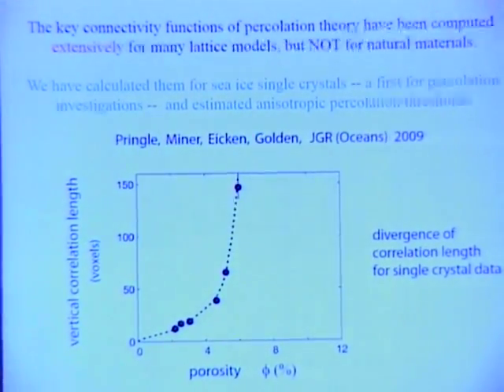Now I've seen hundreds of papers where they compute these functions for lattice models. I've never seen a paper in the literature where they actually do this for real materials. You can't turn a knob, for example, and change the conductivity of pores in sandstone. But in sea ice, they can do that. Change the temperature, and there's a dramatic change in the conductivity and volume fraction of the fluid pores.